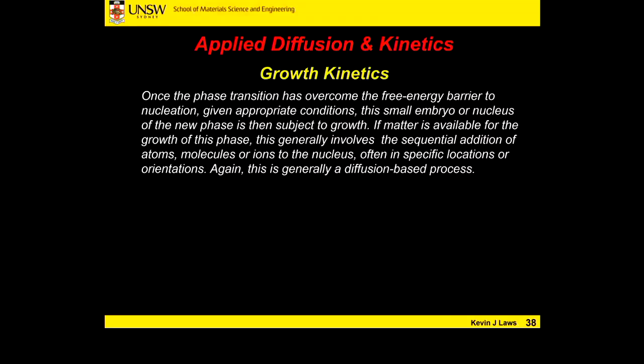A note on growth, and we won't be going into our growth lecture today. We're going to finish up on nucleation because that's a little bit complex. A little bit on growth before we move into our next lecture set. So once the phase transition has overcome the free energy barrier to nucleation, given appropriate conditions, so driving force, temperature, availability of reactants, a small embryo that has nucleated, the nucleus of a new phase, is then subject to growth. If matter is available for the growth of this phase, this generally involves the sequential addition of atoms, or molecules, or ions to that nucleus to make it grow.